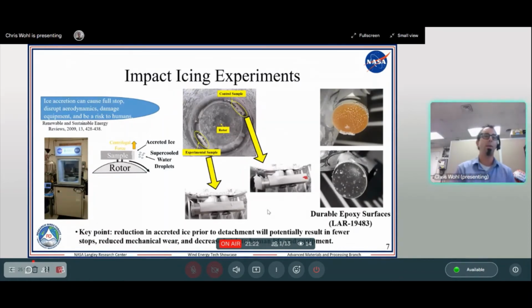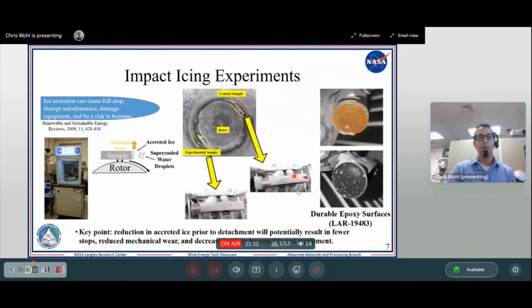So what we have here, we have developed an instrument that can do impact icing experiments. So here down at the bottom, you can see that there is a control sample that collects ice, and then our experimental sample that ice will come off of. And it is the detachment of this ice that we detect. Over here on the right, I've shown a couple of our durable epoxy coatings. This is a different technology. And there's very, very little ice that has accumulated on these surfaces.